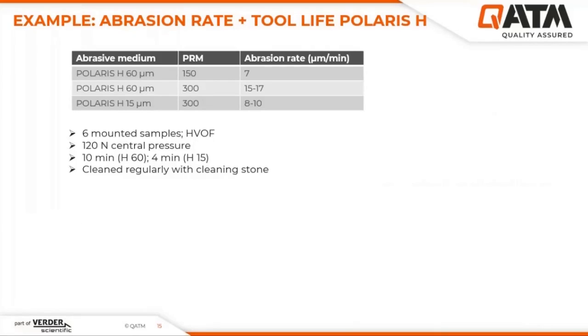Now I will talk about a case study that was conducted with the Polaris H, where HVOF layers were prepared under real conditions with Polaris H discs in the grain sizes 60 microns and 15 microns. They used full sample holders with 6 embedded samples, and the removal rate and the service life were measured. It could be observed that the same disc removes about twice as much at a rotation speed that is twice as high, so the removal rate is more or less proportional to the rotation speed. Of course, the finer the grain size, the lower the removal rate.